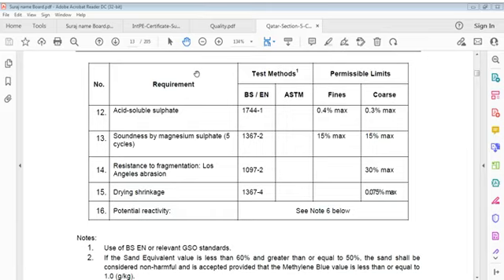Soundness by magnesium sulfate, 5 cycles, 1367-2. Permissible limit is 15% maximum in both cases. Then resistance to fragmentation, Los Angeles abrasion, 1097-2, 30% maximum in case of coarse. And drying shrinkage, 1367-4, 0.075% maximum for coarse. No need for fines. And then potential reactivity.